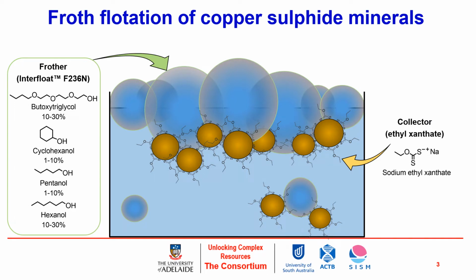Flotation frothers are a class of compounds that are used as surfactants to produce hydrophobically decorated bubbles in a flotation bath. So here we can see that these bubbles rise to the top through a mixture of copper sulfide ore material, and they separate the good quality ore from the lower quality ore through a mediation of a xanthate collector, which decorates the high quality ore particles and hydrophobizes them, allowing them to attach to these bubbles and accumulate at the top of the column. This is then collected and goes through various processes to obtain that copper.